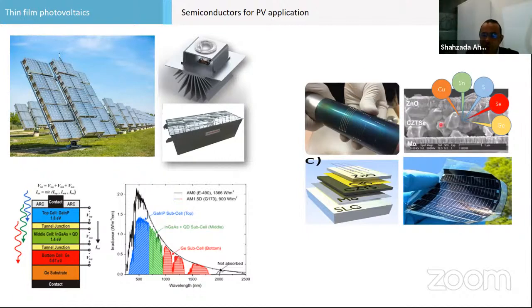And this is a cross-section diagram, which I told you about. You will see that the thickness of these solar cells is 3 micron. And just to give you a flavor, silicon is between 200 and 300 micron. CIGS and CZTS is 2 to 3 micron, and perovskite is in nanometers, 300 to 500 nanometers. So the lower material minimizes the cost.